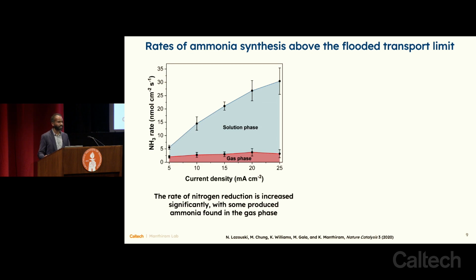And what we found was that what would otherwise be a transport limited rate of less than 10 nanomoles per centimeter squared per second, or even less than 1 nanomole per centimeter squared per second, as shown in the previous report by Sunetto et al. from Japan, we can now reach 30 nanomoles per centimeter squared per second. So we can see immediately that we've actually alleviated this transport limitation. We can now drive much faster rates of interfacial reaction just by implementing this very simple method of contacting gas and liquid at the surface of the electrode.